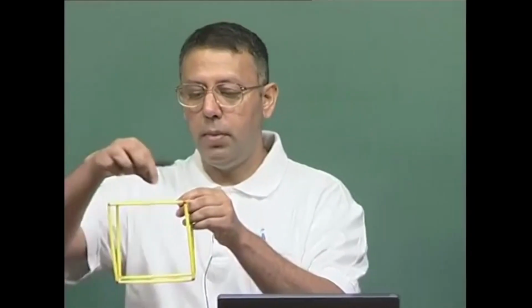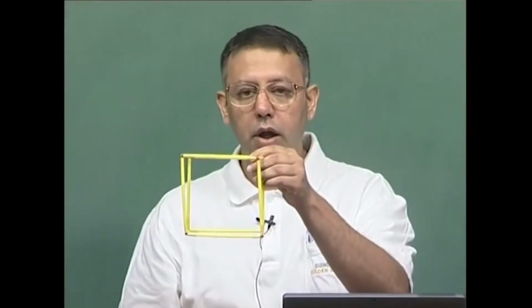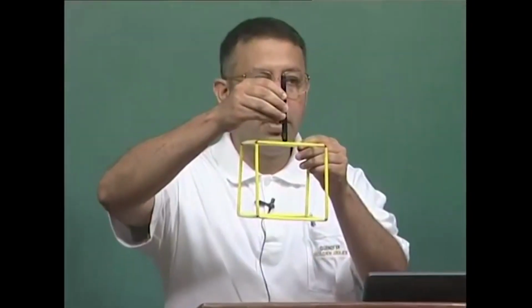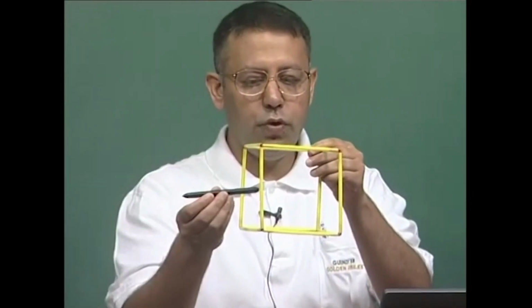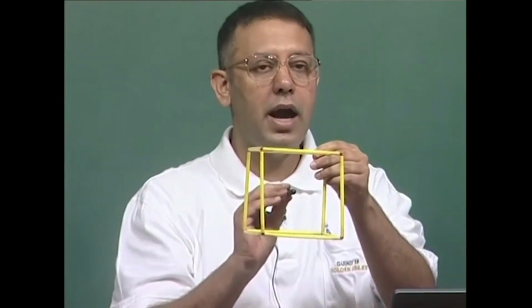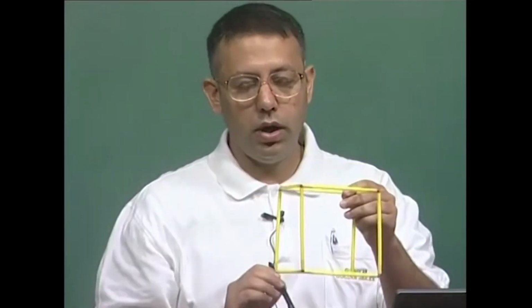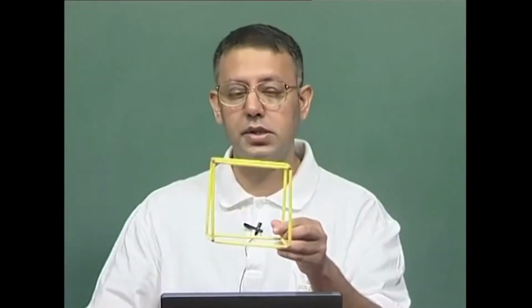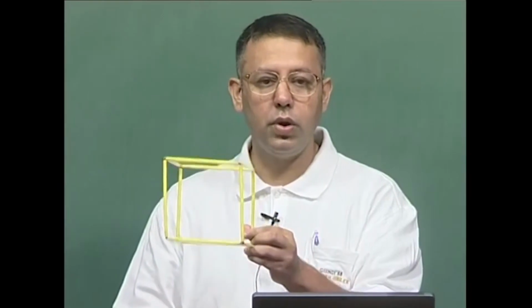Now additionally we will notice that if I do such an operation of introducing a point at the top and a point at the bottom, this 4-fold axis remains as before. This 4-fold axis and these 4-fold axes have been destroyed. Note however that when we are talking about cubic crystals, which we will consider in detail very soon, and this is just a prelude to the understanding of cubic crystals which are based on cubic lattices, cubic lattices need to have this 3-bar or 3-fold rotational axis.